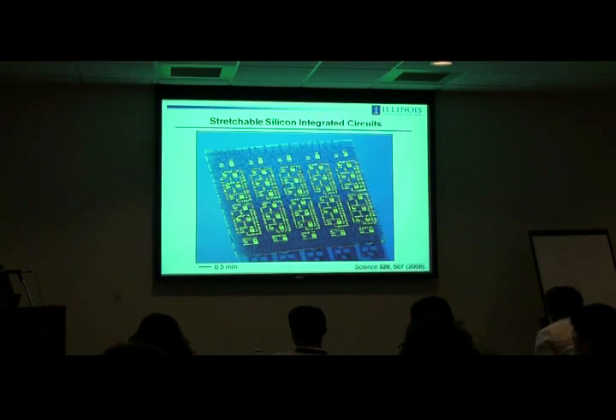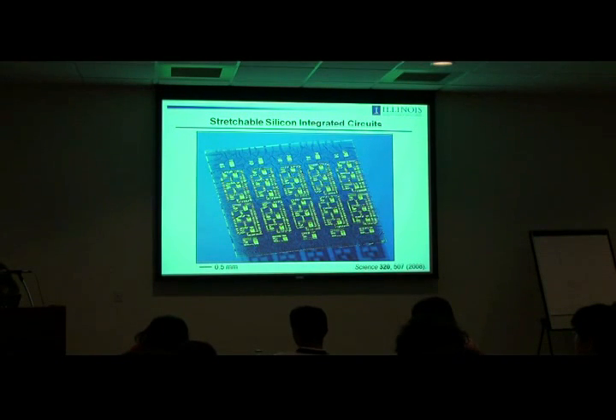It's slightly gas permeable. It's also permeable to certain classes of solvents that you might want to use in a semiconductor fabrication sequence. And so it's useful to separate the elastomer from everything associated with fabrication of the circuit. It also has a very large CTE. So we use the polyimide as a support for fabricating the circuits, and then use that in a final step for integration with the silicon. Polyimide is just a much easier material to work with during circuit fab.